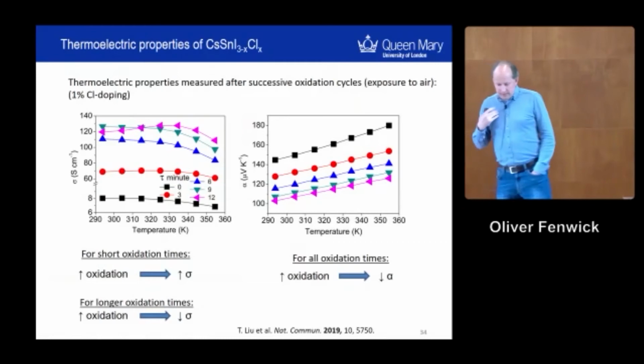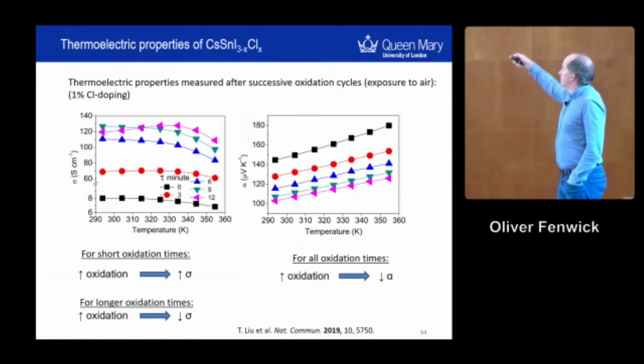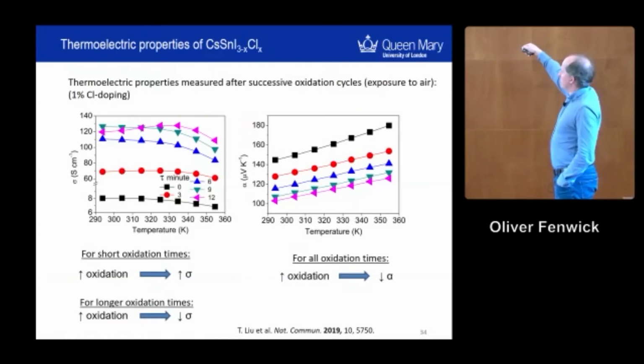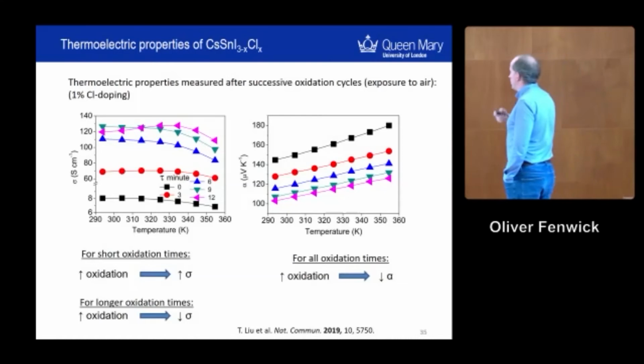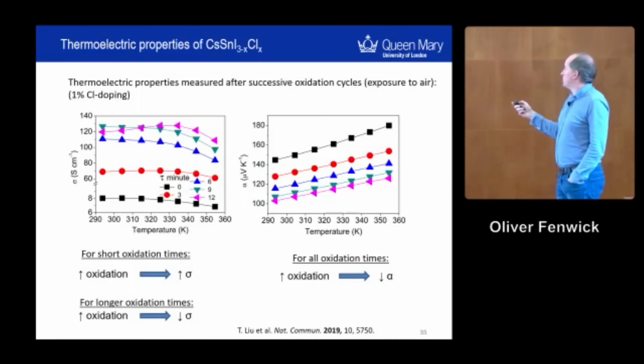Okay, so now the thermoelectric part. In the electrical conductivity, of course, these are temperature-dependent measurements, and we've got a different curve for each air exposure time in minutes, so 0, 3, 6, 9, 12 minutes, not very long, but enough to do some experiments on. So for short oxidation times, we see the electrical conductivity increase, and then for longer times it goes down, as we discussed. But for all oxidation times, we see the Seebeck coefficients decreasing. That's the sign that we are doping the materials.